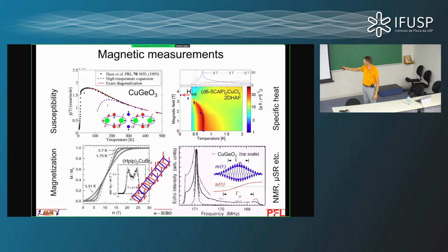I can do specific heat, which works not just for magnetism, but for any material that exhibits phase transitions, and I can track phase transitions as a function of temperature and magnetic field. I can also use so-called local probes. I can use nuclear magnetic resonance. I can shoot muons, which also carry a spin, into the material, or I can use electron spin resonance and locally measure the precession frequency of some spin, be it a nucleus, a muon, or an electron, sensing the local magnetic field inside a material. And that will tell me what the local field is at different positions inside my material.